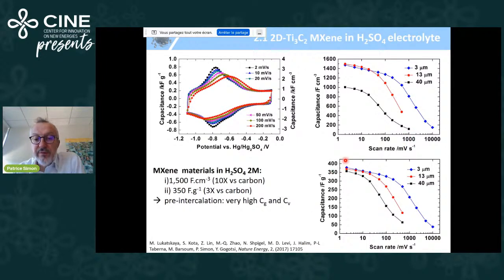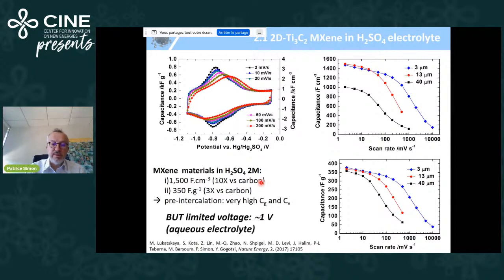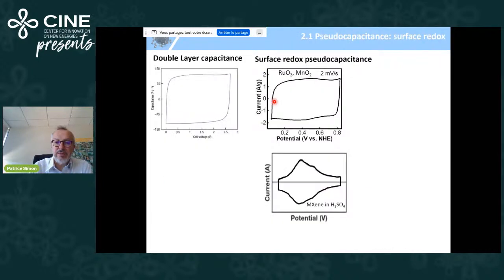Same for the gravimetric capacitance: you have very high gravimetric capacitance, even for a decent weight loaded electrode. So finally, when you use pre-intercalated MXenes in sulfuric acid electrolyte, you end up with super high volumetric capacitance, 10 times more compared to carbon, and high gravimetric capacitance, 3 times higher than carbon. So these are very good results, but the point is that you end up with a voltage window which is only 1 volt or 1.1 volt, limited by, obviously, the water electrolysis. So if you want to increase the energy density of supercaps, this is not very good. You need to move to non-aqueous electrolyte.